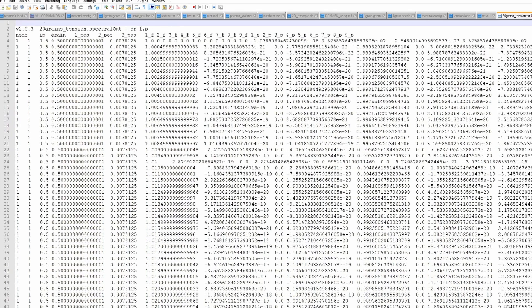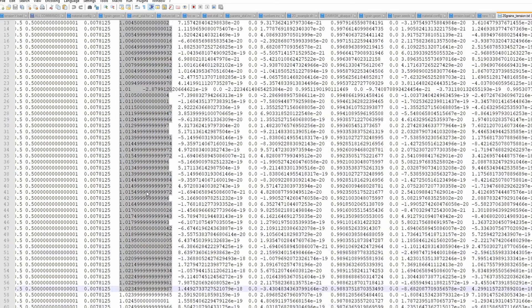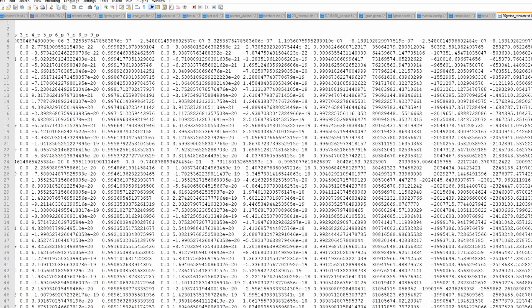Once post-processing is done, a folder is created containing all post-processed data. Opening the file inside, you will see all nine strain components and all nine stress components at each increment. To plot a stress-strain curve, take the column corresponding to the F-dot value defined in the boundary condition and the corresponding stress column. Rename the file so subsequent post-processing steps do not overwrite it.